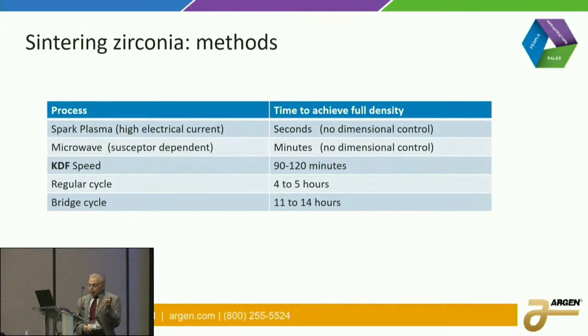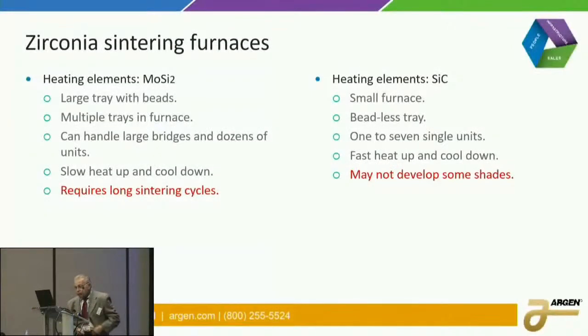And the faster you go with a bridge, the worse the result could be. Now, for small units and single units, we've seen the introduction of this particular furnace, KDF speed, and here the time to achieve full density is like 90 to 120 minutes. So it's a substantially better approach than what we're used to.